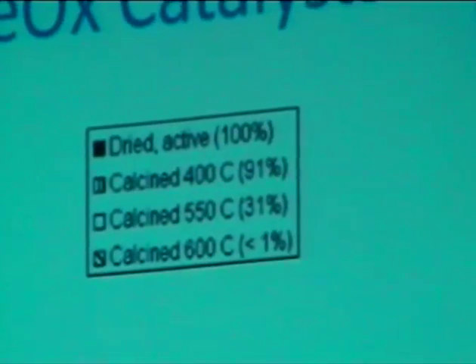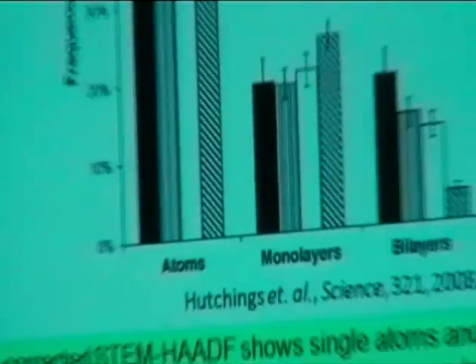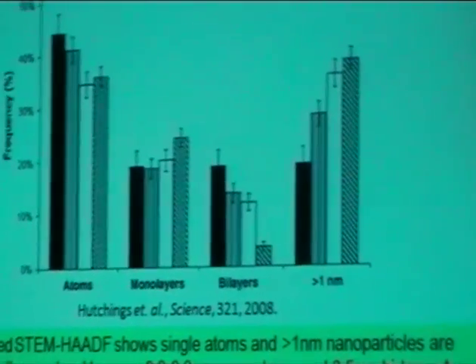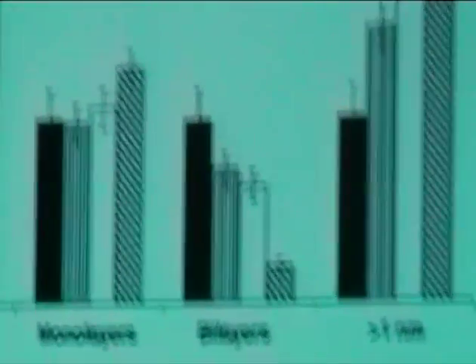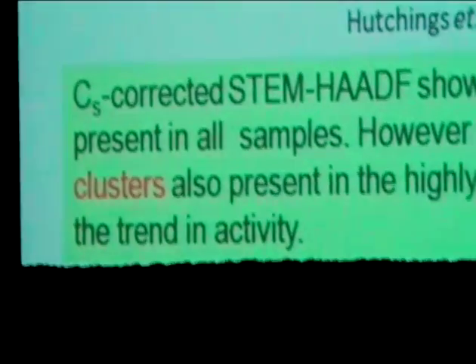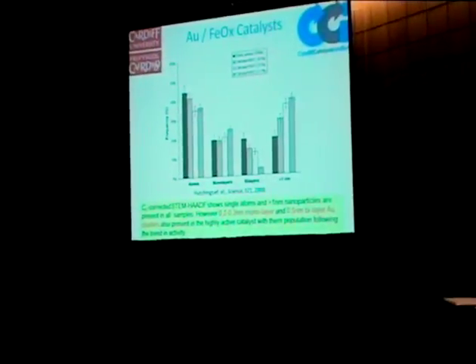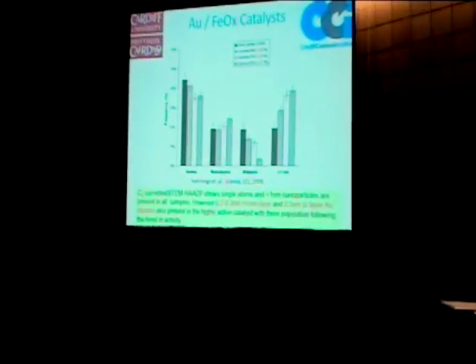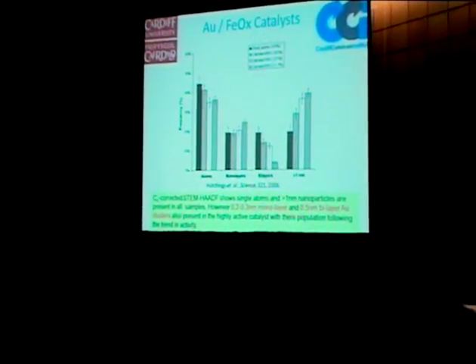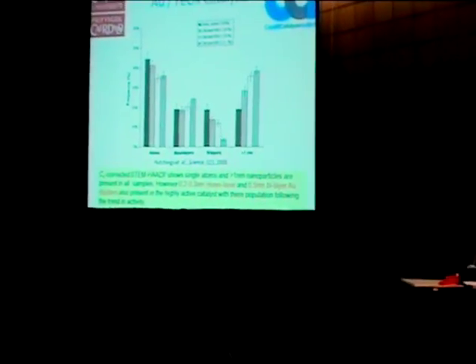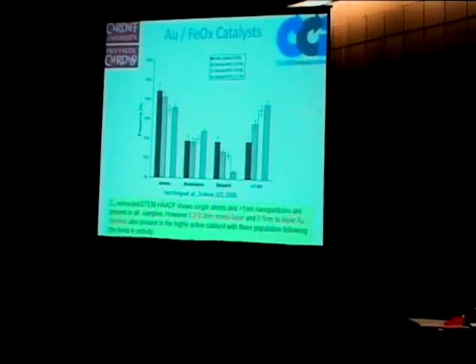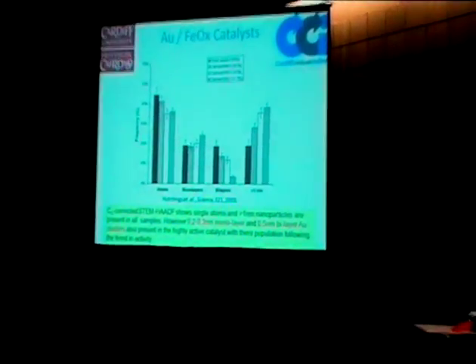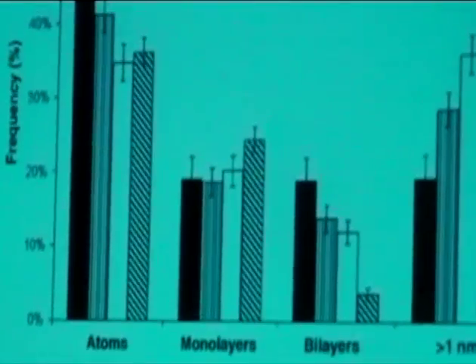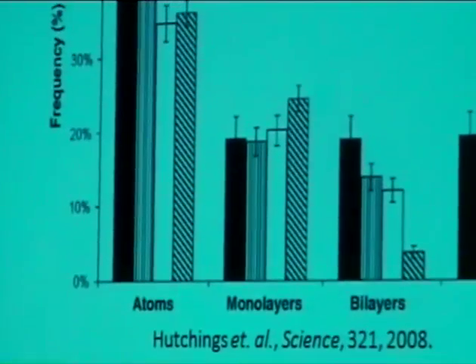So this is a particle size distribution derived from the microscopy data showing the very active catalyst calcined at various temperatures. As you can see, as we increase the calcination temperature, the activity of the catalyst decreases, from 100% activity after an initial drying step to less than 1% activity after calcination at 600°C. So comparing these samples, we can see that as the calcination temperature is increased, the number of nanoparticles increases. This is due to sintering of the gold particles. You can also see that the number of monolayers present in the very active catalyst remains fairly constant through the calcination procedure.